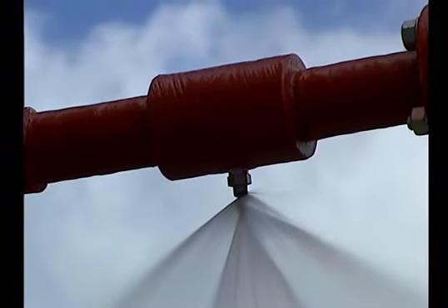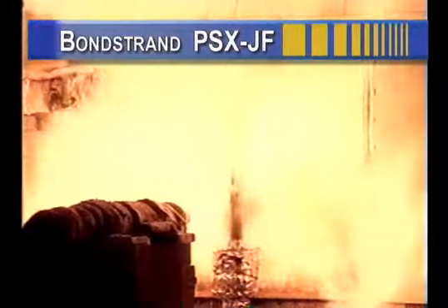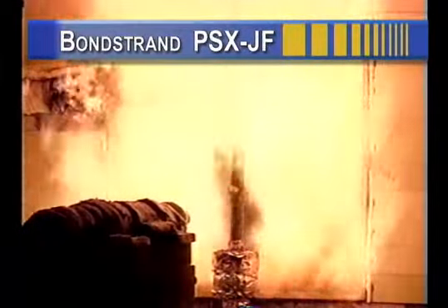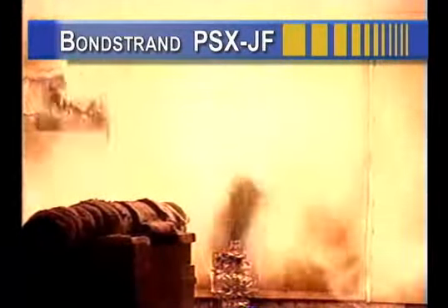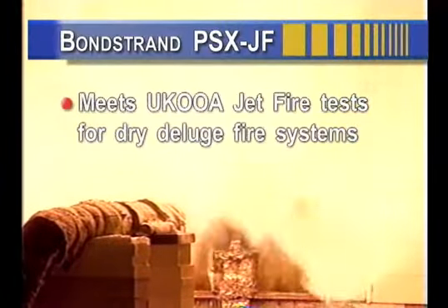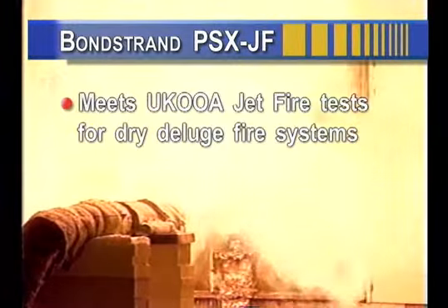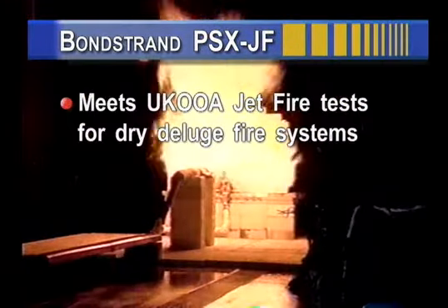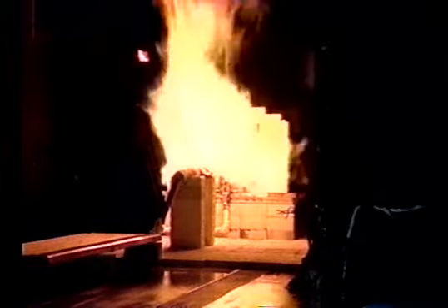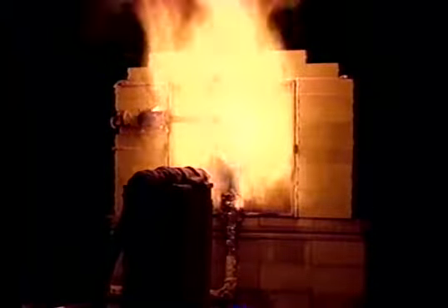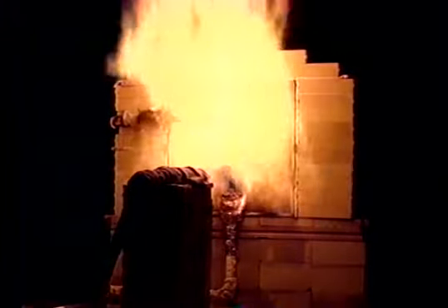Bondstrand PSX JF is designed to endure a fierce offshore hydrocarbon jet fire at 1100 degrees Celsius. In the UKOOA jet fire tests for dry deluge fire protection systems, the pipe and fittings are exposed to a jet fire for 5 minutes dry, followed by flowing water through the test sample for 15 minutes at 150 psi and 1100 degrees Celsius. This creates a heat flux of 300 kilowatts per square meter and consumes 5 kilograms of propane per hour.